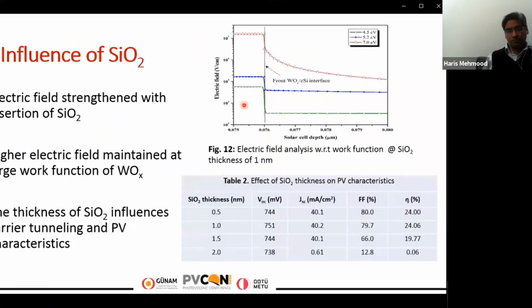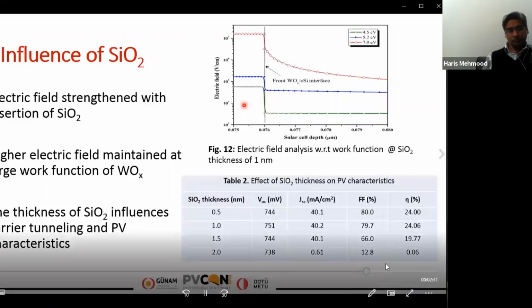So by inserting the silicon dioxide layer, we have been able to maintain the electric field within the oxide layer as shown in the figure. And that electric field will try to accelerate the holes towards its layer, because of a tunneling process across the silicon dioxide layer, and it will be then ultimately collected at the anode terminals. So the high electric field has been maintained with a large work function of tungsten oxide (WOx).